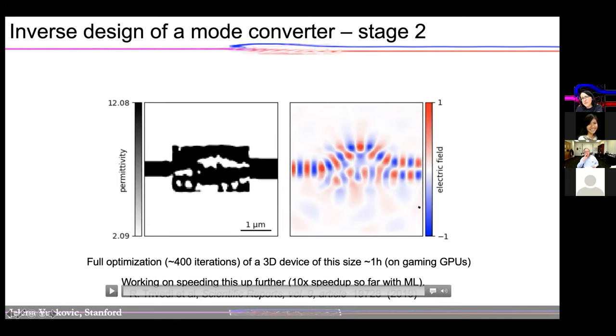And I should emphasize that this is fully three-dimensional. Here you see only a two-dimensional image, which is a cross-section of the device, but the optimization is completely done in three dimensions. And we constrain the geometry to a single pattern in one planar layer because that's something that we can easily fabricate. And of course, for in-plane planar photonics, that's what we prefer to do. At most, we go to maybe a couple of layers. But since you're using three-dimensional optimization, you can design something with arbitrary patterns in three dimensions. And if you can fabricate it, that of course gives you even more degrees of freedom.